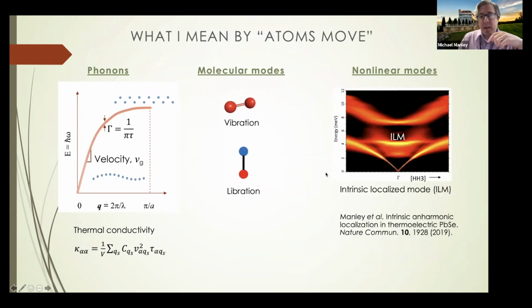The third example that I will talk about in the second half of the talk is basically, I'll start talking about nonlinear modes. So this is kind of the more advanced part of the talk. And I will talk specifically about intrinsic localized modes. So you have your phonons here. These are your normal phonons, but in addition to the phonons, you get this extra patch of intensity that pops up here, which represents an intrinsic localized mode, which is interesting if you're looking at thermal conductivity because it is a mode that isn't propagating. So you basically locked energy in, and it occurs in a perfect crystal, which turned out to be very interesting from the point of view of a thermoelectric, where you want to stop the heat from flowing, but allow the charge to flow. And so I'll talk more about that in the second half.